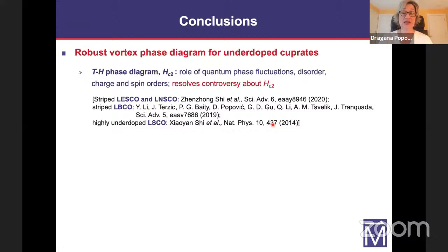And concerning transport, I know that Suchitra Sebastian has reported some transport measurements at conferences, about the regime of fields where resistance depends on the applied current. And this was discussed in terms of fragile superconductivity by Steve Kivelson, for example. But I want to emphasize that this is precisely what you expect in the vortex liquid regime. So to me, at least, it seems that this is not really specific to cuprates. This is what you would expect for all type 2 superconductors that are reasonably clean.